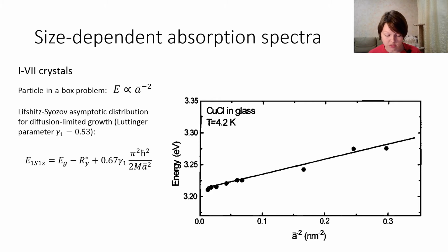However, in the case of the finite size distribution, the experimental peak position differs by a constant coefficient all the time, compared with the theory. And now this formula we can use while fitting the size dependence of the position of the Z3 free exciton absorption band.